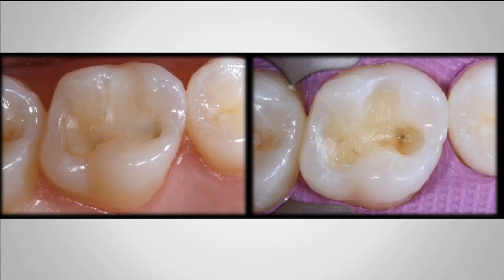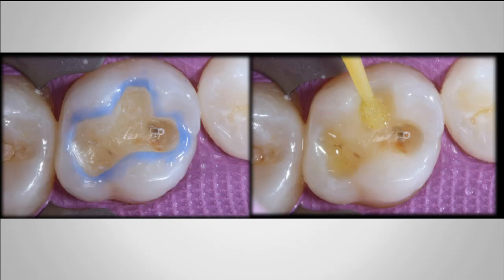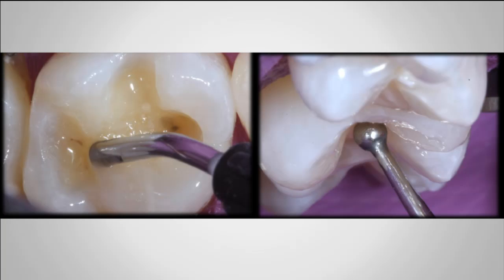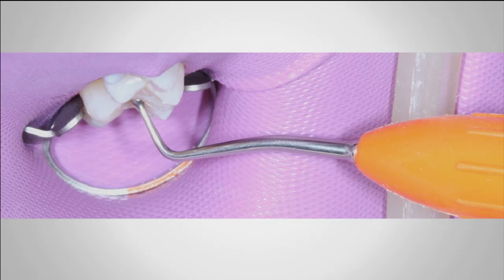What we do nowadays, we just remove the old composite. You know already that we don't etch the dentin, we just etch the enamel for 15 seconds, 20 seconds. After that, I apply a universal adhesive like this. After applying this adhesive, I will polymerize this layer. And the way that we use for posterior restoration nowadays is filling all the cavity with a bulk fill flowable composite, leaving just a small space for the last layer.